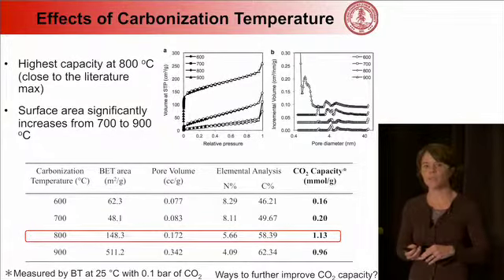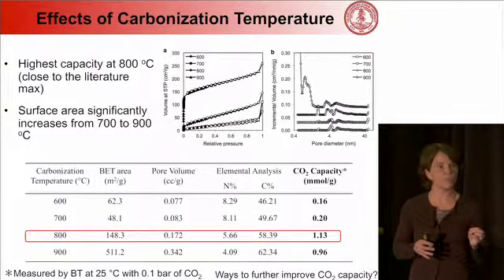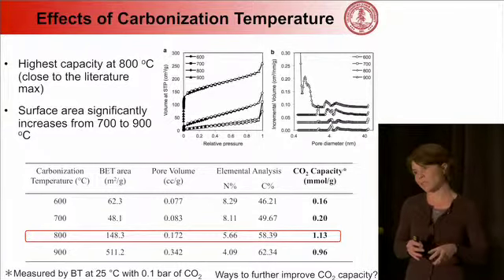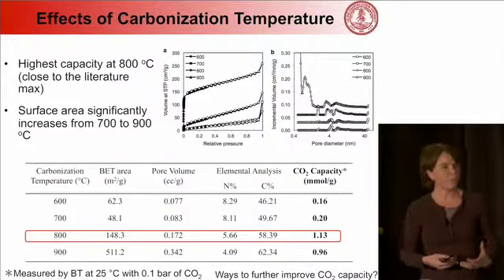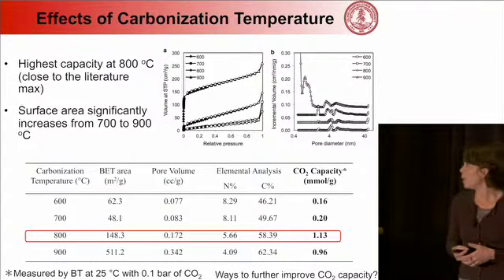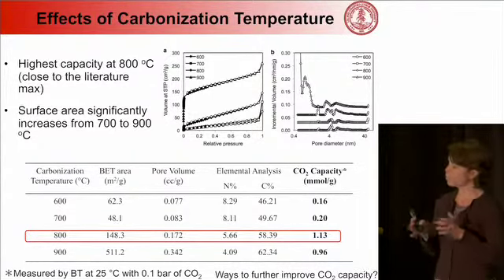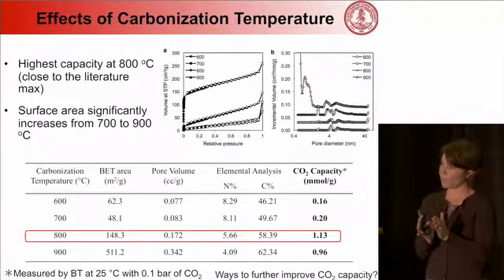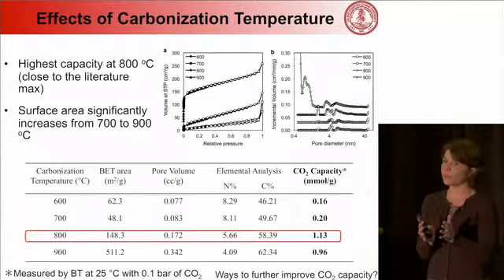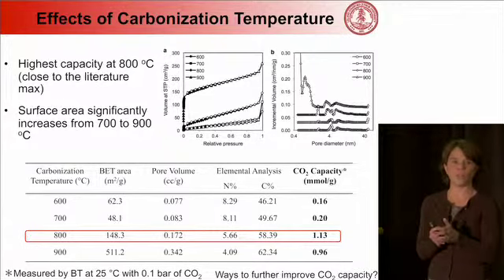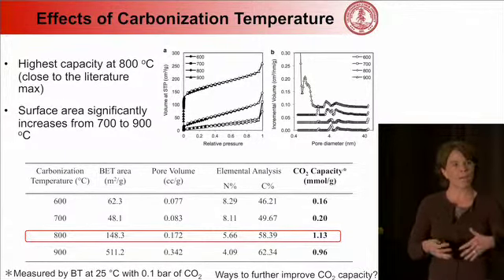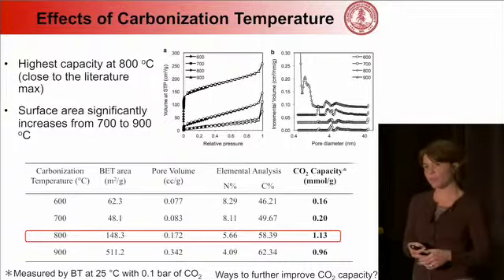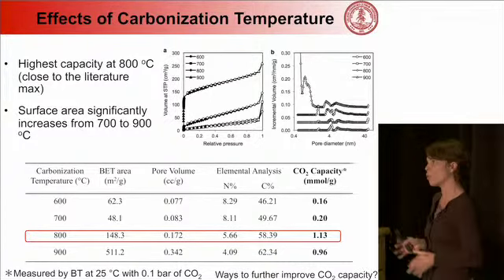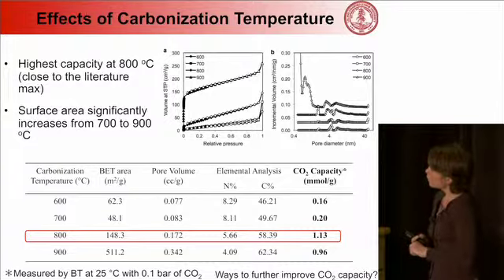But the other aspect is that you have a duality between the CO2 interacting with the surface and the CO2 interacting with itself. So CO2 has a self-interaction just like water does. And so what we want to try and do is tune the pore size so that we actually get both CO2 interacting with itself and the surface of the pore. Because if we can get the self-interaction, then we have a condensed phase, and that will enhance the uptake. So there's two driving forces that we're interested in when we tune the pore size and the chemistry of the